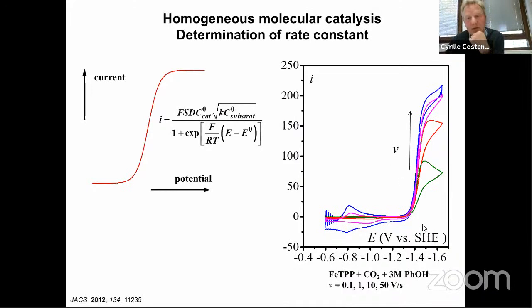Now, if you increase the scan rate, of course, you decrease the time scale of the CV, and so the charge that you pass is smaller. And so you can reach this plateau now, which is the ideal situation. And you can see that at two different scan rates, you get more or less the same current, which means that you have reached a steady state where you can get the kinetic information from the plateau here.